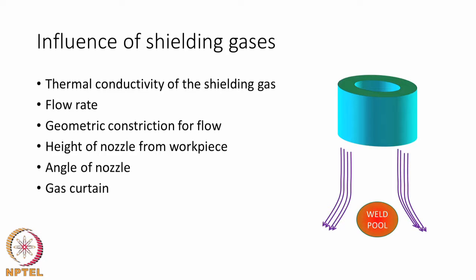And how far the gas nozzle is from the workpiece also plays a role. The reason being that as the gas is expanding and mixing in the ambient air, its velocity also drops. If the nozzle is very close to the base material, then the gas has a significant amount of momentum and the heat loss will be more, and if it is very far away from the base material, then it may not be taking away much heat. So, we must also know the height of the nozzle from the workpiece.